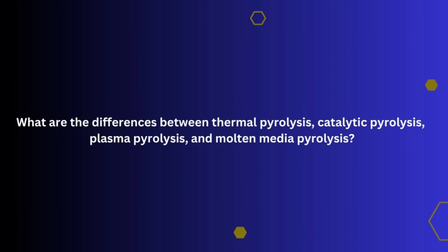Now, how to get the temperature to the methane. One of the most widely used systems is using a plasma, which is an ionized gas that is composed of highly energized particles. And that high temperature heat in the plasma cracks the methane. The temperatures are extremely high, so they can go up to 10,000 Kelvin, and then you don't need any catalyst. So you don't have all the issues associated with catalytic materials, as I mentioned before, the coking, etc. So you don't have that with plasma.